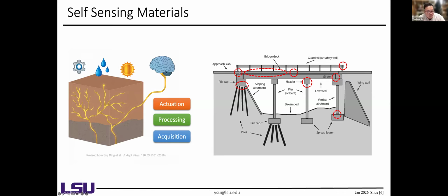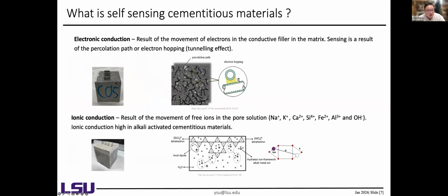Since this material is not cheap, we are targeting to embed it in specific or critical areas of the structure. Let me give you a brief introduction of self-sensing cementitious material. Self-sensing works through two mechanisms: electronic conduction and ionic conduction. Electronic conduction incorporates conductive filler into the cement matrix, and then we can obtain an electronic signal from that. Ionic conduction is based on the movement of free ions in the pore solution, intrinsically built into the cementitious material. Specifically for high alkaline active material, it's abundant.